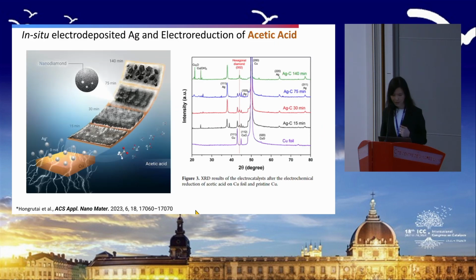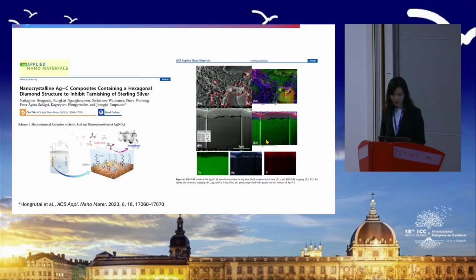This is the effect of the reaction time. The diamond actually occurs even at the beginning, at 15 minutes. If we look at the figure here, we will see that the silver actually deposited first, and then we have the carbon formation. And then afterward, we have another silver coming and covering it.